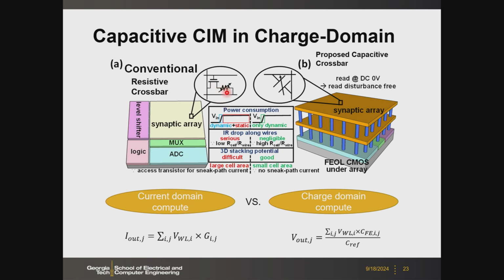And the challenge there is that when the resistance is low, especially in on-state, at least from our foundry friends, what they offer to us, the resistance is low. Therefore, when the input is high, we are going to pass a static DC current through this resistor. So we spend a lot of static power here. But if we change this to a capacitor, by its nature a capacitor only consumes transient dynamic power in the rising edge or the falling edge. So we eliminate this static power. This could reduce the power consumption significantly. And also because we do not have the current through, the IR drop is also mitigated.